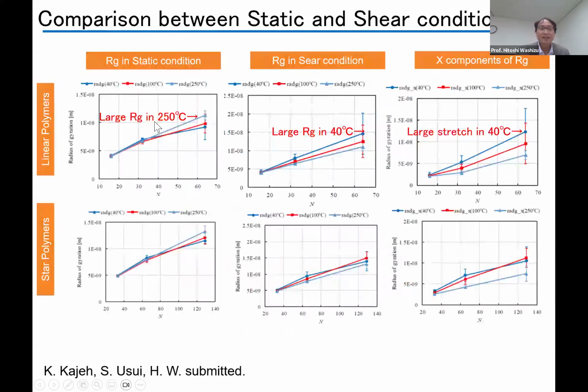What's happening is that using this simulator, it is very easy to look at the static condition and the shear condition. Okay, let's see. In the static condition, there's no shear, and the radius of gyration, the size of the polymer, is larger in the high temperature. But in the shear condition, it is different. In the high temperature, it is low. What's happening here? This is the X component. X means the direction of the shear.